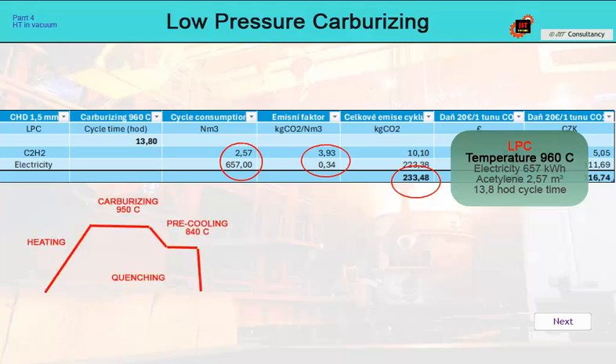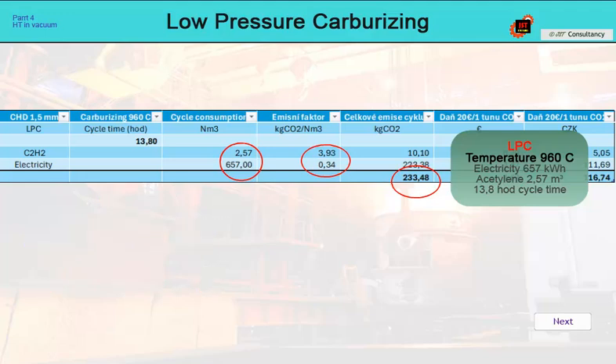If we were to carry out the same process in multipurpose furnaces, the situation would be as follows. We have to go down in temperature, because the maximum temperature on Ipsen furnaces is 950 degrees Celsius. We will have an endo-type atmosphere and the addition of propane for carburizing.